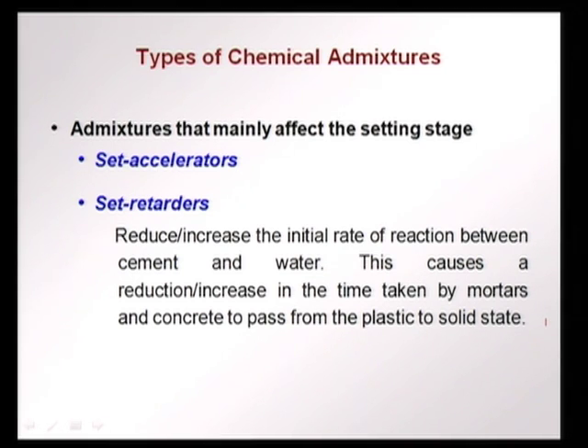Suppose we want setting to occur very fast, say in the case of shotcrete, where we shoot the concrete onto a surface, the concrete has to stick there and not fall off, or we have a case where it is a very cold temperature and we want the concrete to act very fast and not set very slowly, or we are in a hurry to finish a certain type of structure, we can use a set accelerator. Setting is faster and the reactions occur faster.